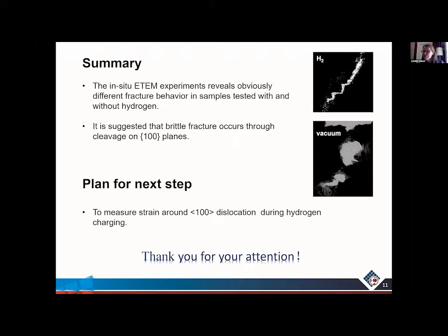Well, that's very interesting. Of course, in the TEM experiments that Lynn spoke about, we would like, as she mentioned at the beginning, to introduce additional gases to test exactly the work that Professor Kubota is doing. One thing we could conceivably do in our TEM, with the use of EELS, is to look to see whether we're changing the electronic properties near the surface. So I think this is an interesting thing for us to think about and see whether this would be useful for comparing with the MD simulations and the DFT simulations. For me, this will be amazingly useful. I would love to see such experimental support.